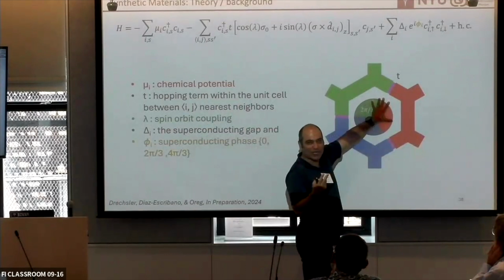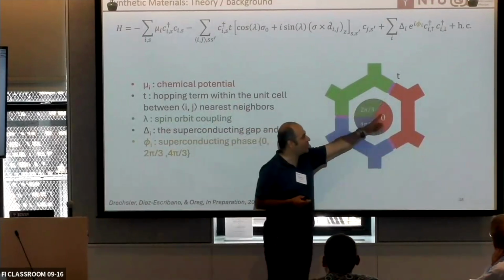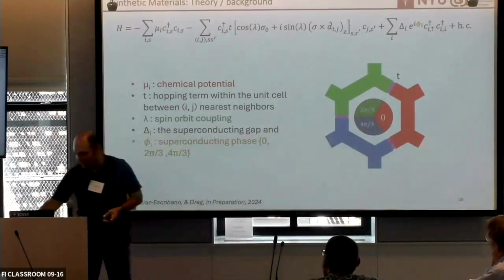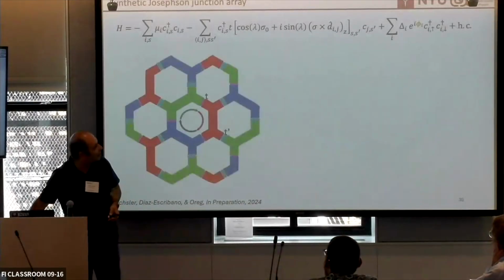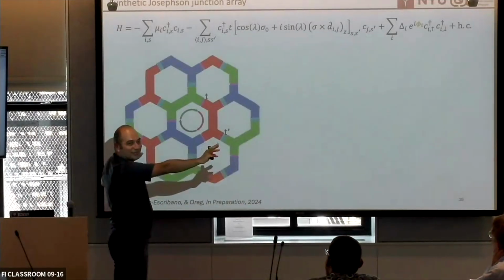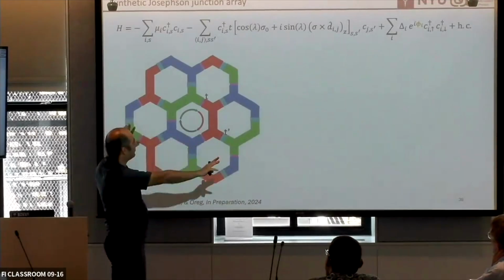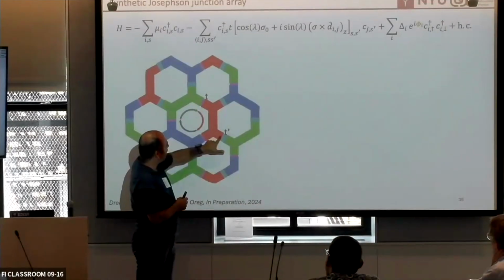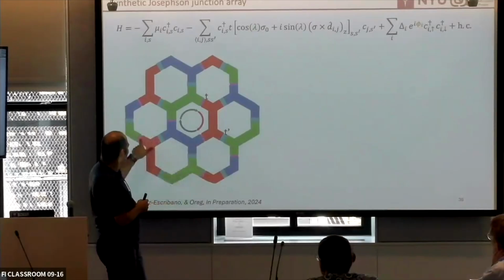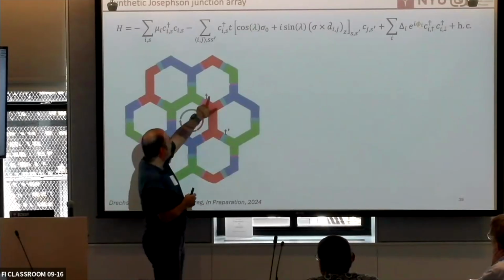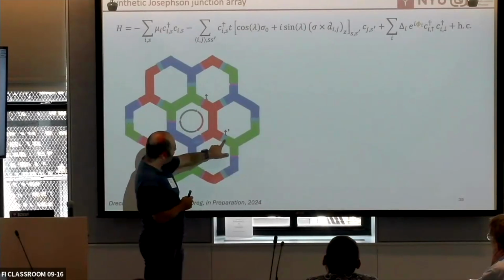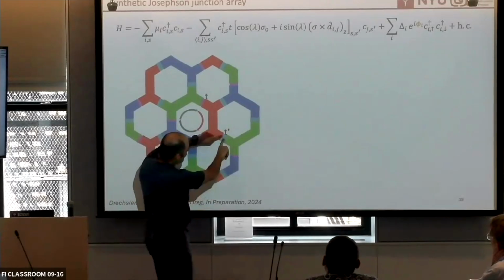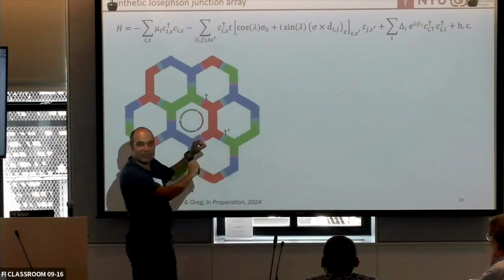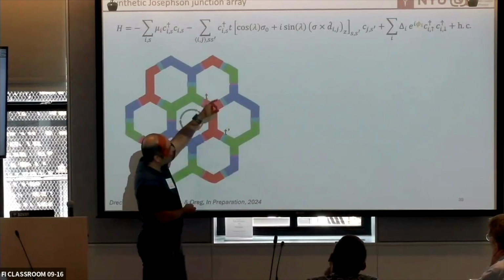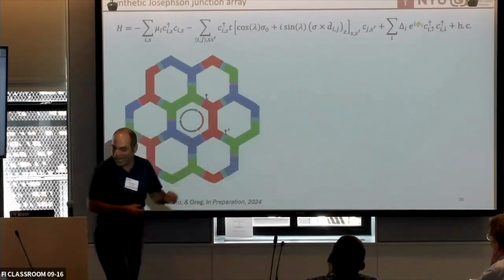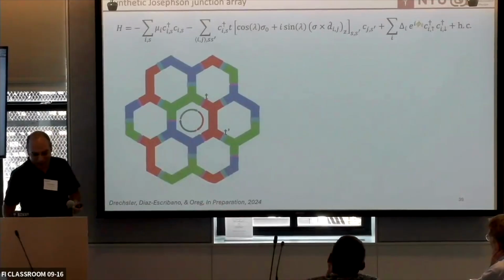And remember, in superconductivity, the phase is special, so I can actually make the phase wind in one of the cells. And better than that, I can actually create a carpet of this hexagon, exactly like graphene. I can carpet it and basically change the way that these couplings are happening in my carpet. In this particular case, I have a T, which is a strong coupling, and a T prime, which is a weak coupling, just because the junctions are separated from each other a little bit further, right? So I have basically in my Hamiltonian a T over T prime that actually gives me a phase space for how I can go to topology.